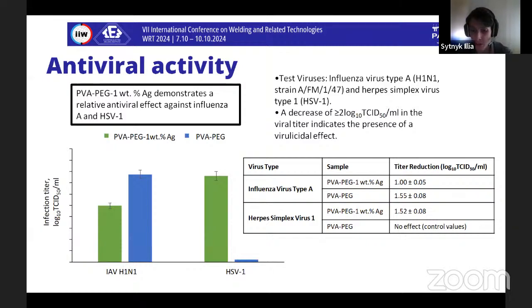Thus, relative to influenza virus type A, composites PVA-PEG with silver and PVA-PEG with no silver showed a weak virucidal effect in the range of 1 logarithm and 1.55 logarithm titer reduction, respectively. Regarding the herpes simplex virus, the PVA-PEG sample did not show a virucidal effect. The virus titer was within the control value, while the PVA-PEG with silver composite reduced the virus titer by 1.52 logarithm.